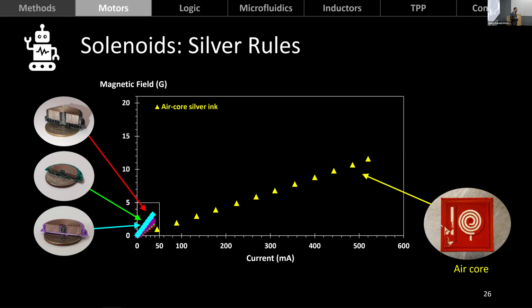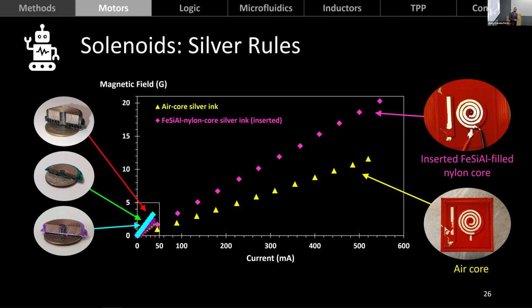And both with an air core and even better with a magnetic core. Now this improvement in magnetic field is mostly by virtue of being able to carry higher currents. And so the limitation for the magnetic fields that we are able to get is mostly due to the resistance of these devices, because the resistivity of the materials is quite high. When we put a current through them, they heat up, and at some point they start to deteriorate. So that limits how much current we can put through and how much magnetic field we can get out of them.